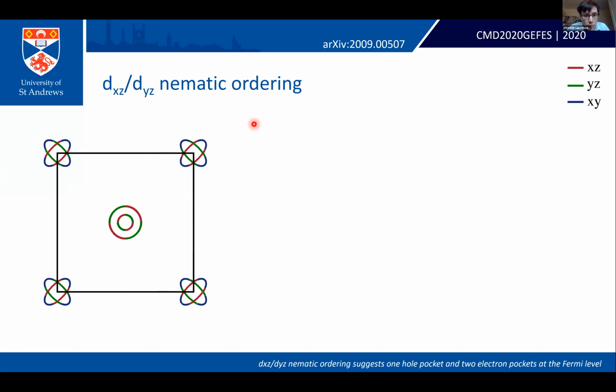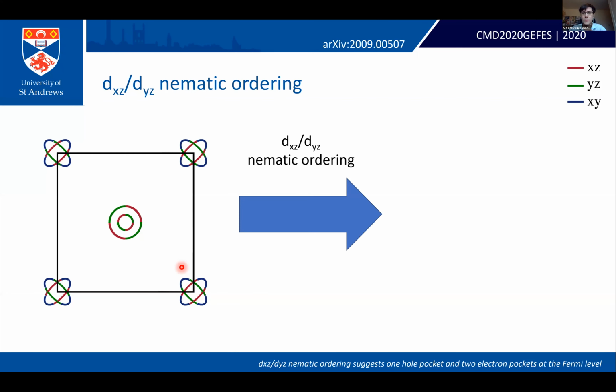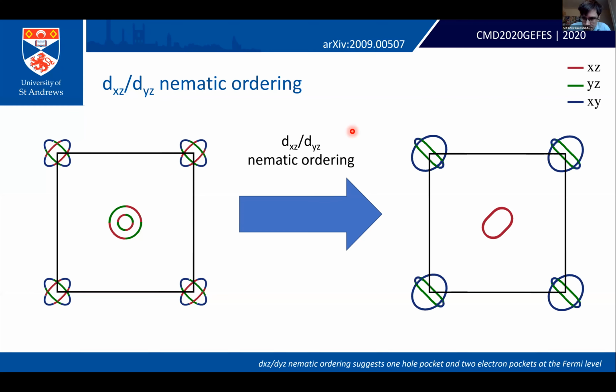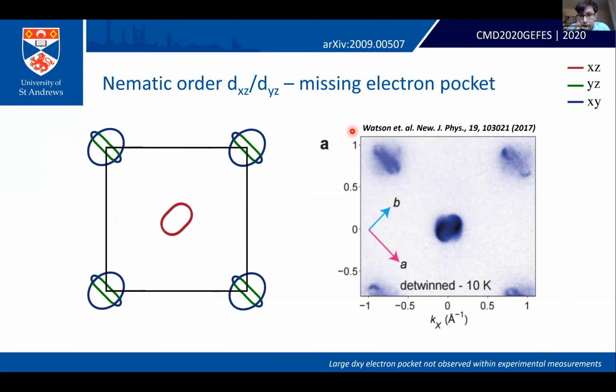What I mean by that is, if we were to take a model of the electronic structure of iron selenide and apply to it a nematic order parameter that takes into account this rotational symmetry breaking and the lifting of the degeneracy of the XZ and YZ orbitals, then the best possible Fermi surface you can obtain looks like this. And this Fermi surface does capture some of the properties that we observe in the experiment. It captures this elliptical hole pocket, that's this one. And it even captures this peanut-shaped electron pocket that we can see in the ARPES data, which is this one here.